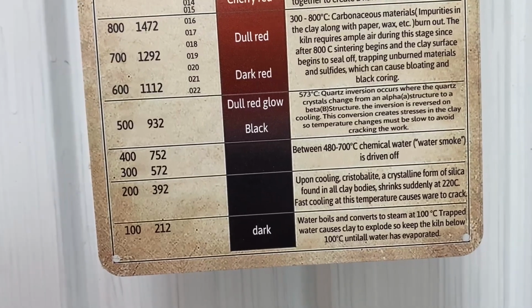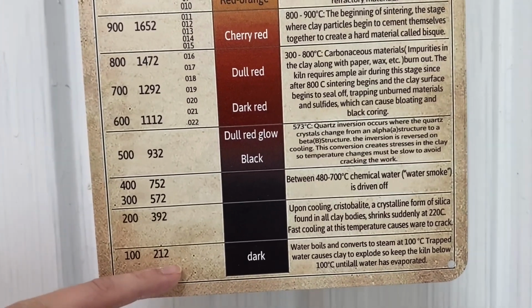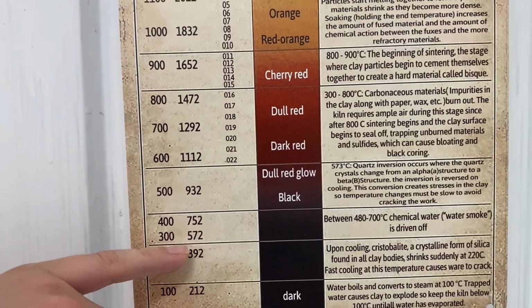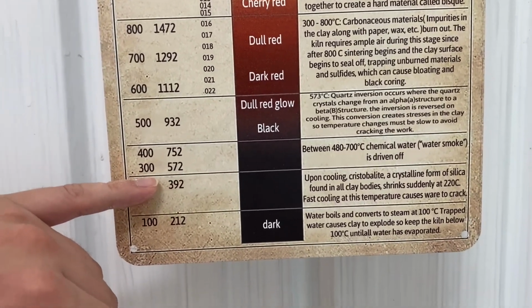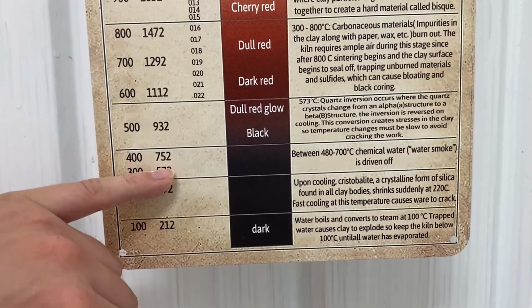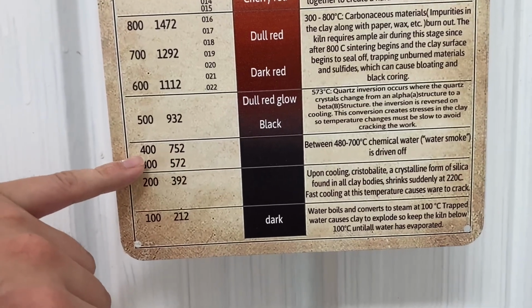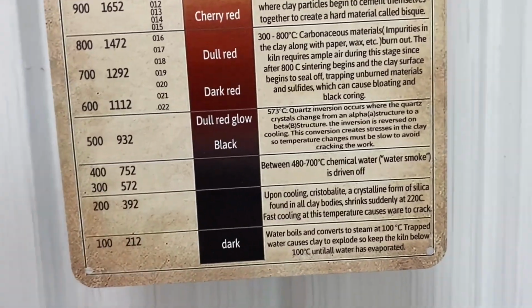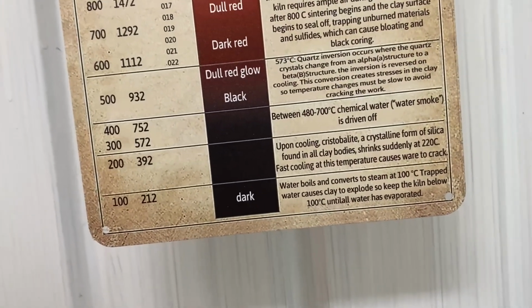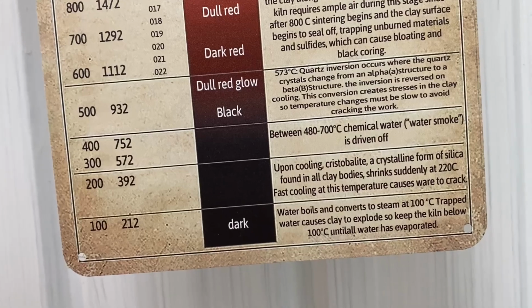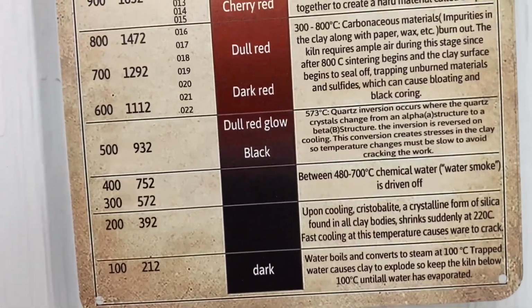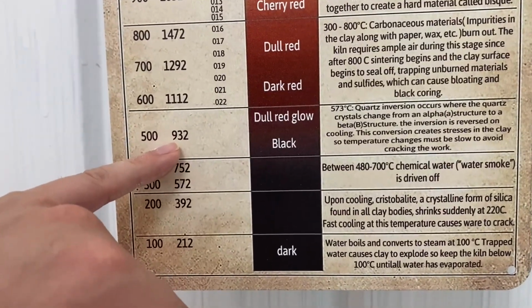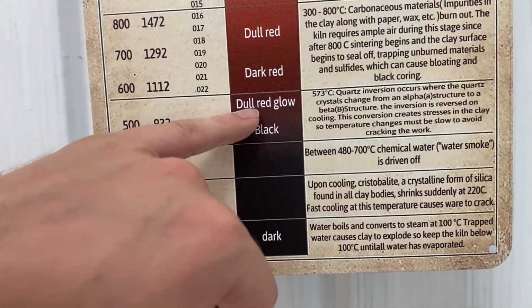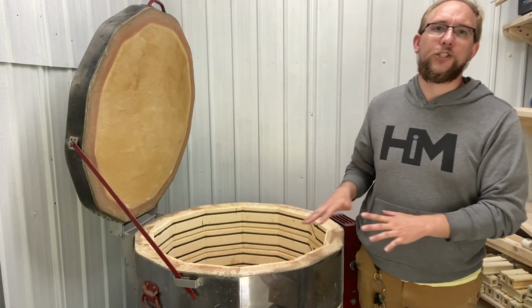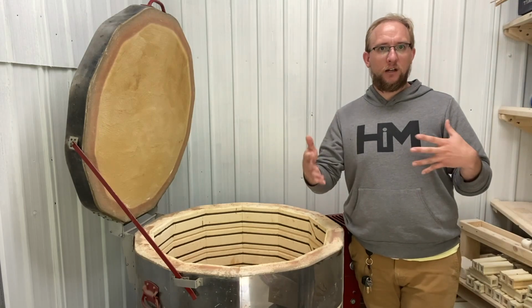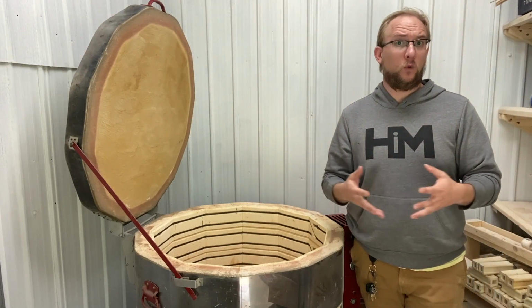Okay, so here's a chart for our reference. As we warm up the kiln, it's going to be dark, dark, dark. We're going to see some progress in regards to our purpose at 752 degrees Fahrenheit, or 400 Celsius, and it's between the 480 to 700 that chemical water, or the gases, or the water smoke is actually driven off, which is what we want. We start to cure our kiln wash at 932 degrees. What we're going to see is a dull red glow. So I take the 1-inch column and I just go ahead and stack them up. You just need enough room to have the kiln wash dry, right?